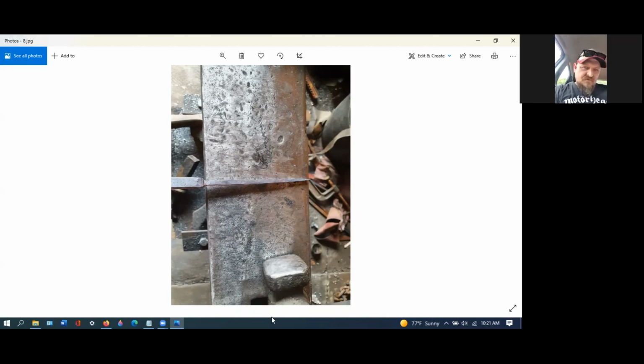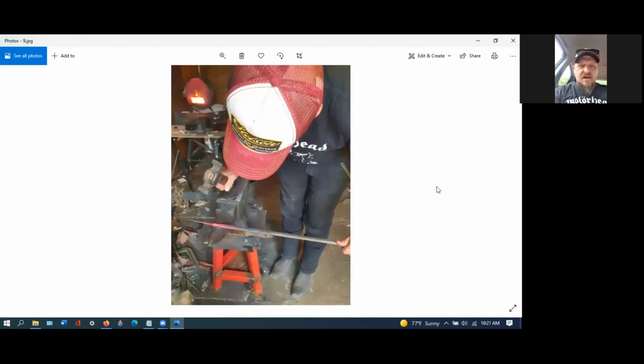That tang is roughly, I'd say my anvil's about 4 inches wide, so it's about 100 millimeters long, that one. That's what I was talking about earlier about wasting the neck on the horn of an anvil. You're pinching in to create the hourglass shape that a lot of arrowheads have. It also helps. You're not removing material by grinding. You're pushing material into the end, towards the point.